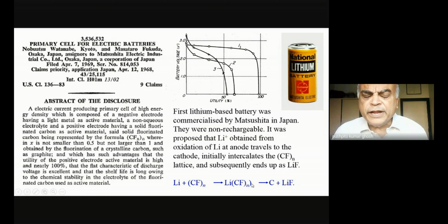Why? Because fluorine is always wanting to stay as F minus. It's the most electronegative element. So effectively, they took the most electropositive element known, which is lithium, and the most electronegative element known, which is fluorine. And they ended up converting this back into carbon, the graphite, and lithium fluoride. So the real driving force for this particular battery was the tremendous stabilization they got from formation of lithium fluoride, and that is what was driving their battery.